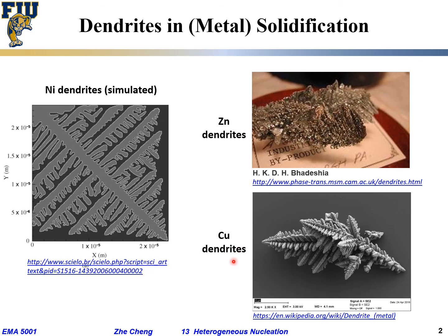In actual experiments, people observed crystal dendrites for pure metals — for example, this zinc dendrite as illustrated, and beautiful copper dendrites observed in photographs. Dendrites do appear even in pure elements under special conditions — the so-called supercooled liquid condition. On the other hand, if the liquid is superheated, we would have a planar interface and dendrites will not form.